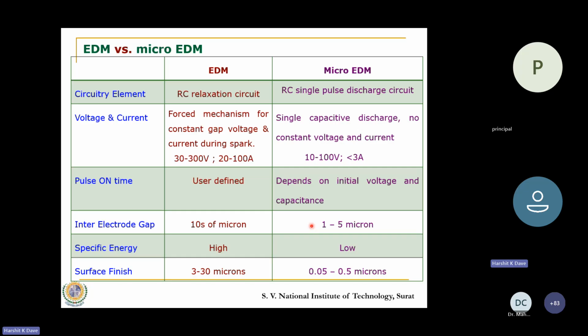In the regular EDM process, the voltage range is from 30 to 300 volts, and the current ranges from 20 to 100 amperes. Of course, those machines have the capability to go down to 5 or 3 amperes, and up to 10 volts also. But the usual range is 30 to 300 volts and 20 to 100 amperes. Now, when we go to micro EDM, the voltage goes up to 100 volts and the current is less than 3 amperes. Not only 3 amperes or 2 amperes or 1 ampere; you use current in milliamperes also.